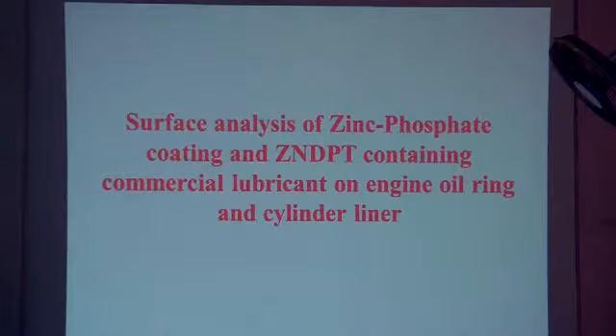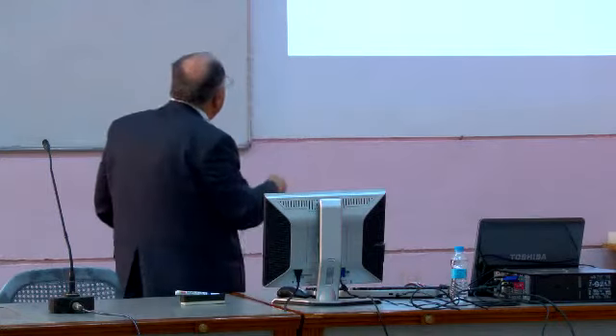Now we think that it is high because it shows more adhesion. We are searching now into this, because of the viscoelastic effect of additives. It is difficult, they are more sticky when you do measurements by AFM on the tip.